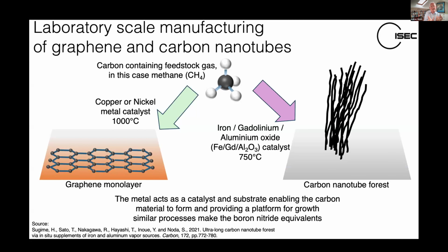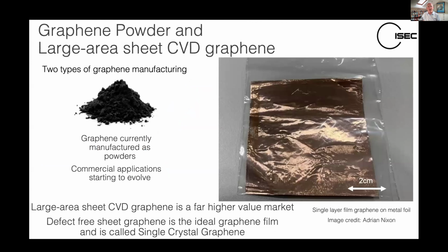The carbon lands on the surface, and the metal acts a bit like a dating agency for carbon atoms, and they self-assemble in this hexagonal chicken wire form as a monolayer or sometimes multi-layers, depending on the reaction conditions on the surface of the metal. Carbon nanotubes are grown by a similar but slightly different method where the carbon is dissolved into the metal catalyst, and these are quite complicated catalysts, but basically a forest of fibers will grow out from the surface. In both cases, the metal acts as a catalyst for growing either the flat stuff or the tubes.